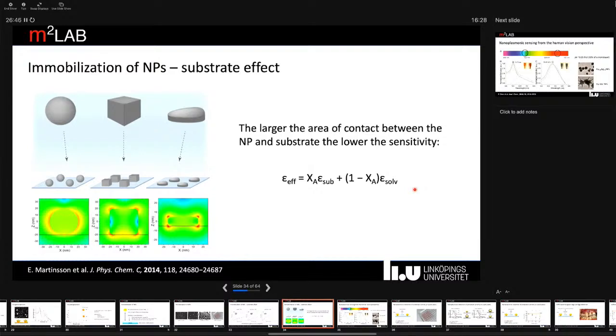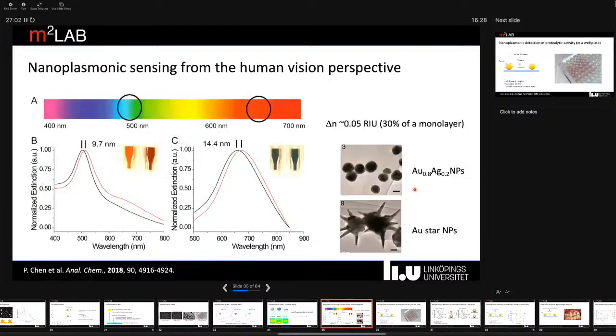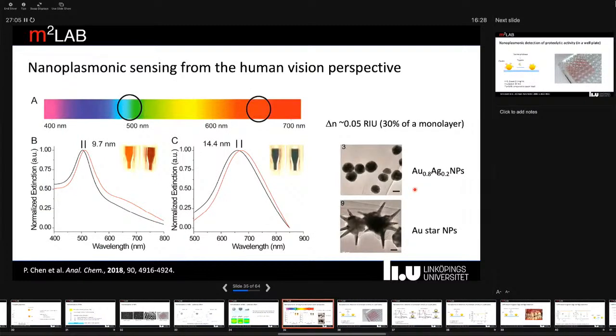And these differences are typically what we are talking about now with these particles. We typically rely on a spectrophotometer to monitor these changes in refractive index, but we can also, with some tricks, make them visible by naked eye. That requires that we take the physiology of human vision into account. We can boost sensitivity by redshifting the plasmon band, to have particles that produce a large shift in the plasmon band as a result of fairly small refractive index changes.